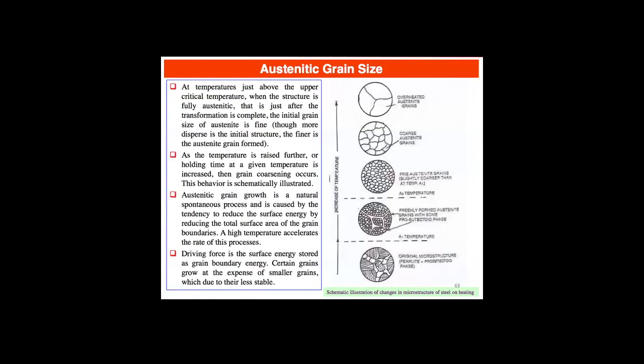Is this hypo or hyper? Right, we've got hypo. It's hypo, right? Yeah, because we've got nice, clean ferrite grains that grew as pro-eutectoid ferrite, right? So basically, we can trace out what our prior austenite grain boundaries were, right?